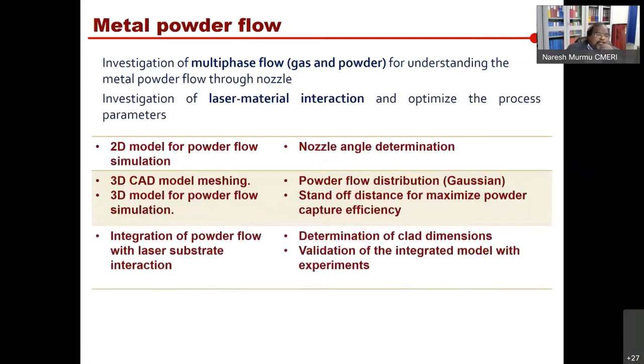So in the numerical simulations, first we tried to investigate the multi-phase flow, the gas and powder, to understand the metal powder flow through the nozzle. That is one of the requirements, and second was investigating the laser material interactions and optimizing the process parameters. So what we did here is a 2D model for the powder flow.